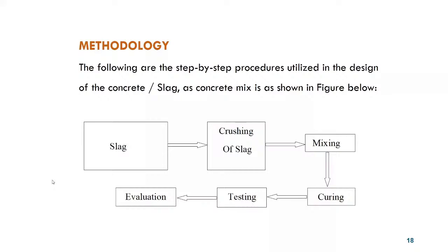Now, the methodology adopted in the research was the procurement of the slag, then the crushing of the slag to 20 mm size aggregate, then proper mixing and proportioning of the slag with the regular constituents of the concrete, then curing the concrete blocks, and then testing and making the evaluation depending on the results. The mix proportion used here was 1:1:2. We adopted the nominal M25 mix, and the water cement ratio was 0.5 by weight.